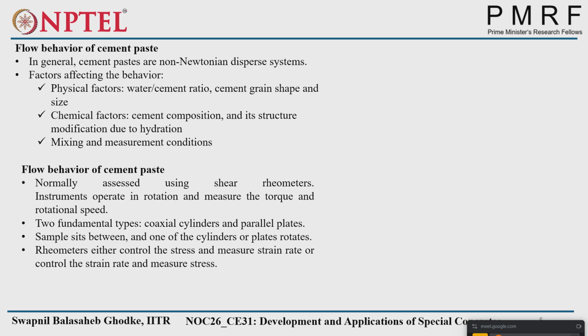Further, shear rheometers that are normally used generally operate in rotation. They rotate, that is, give the shear and measure the torque and rotational speed as raw data. Then we plot that data and go for further analysis. Two fundamental types of rheometer are generally used: coaxial cylinder and parallel plates. The sample generally sits in the gap between these two types of equipment. This sentence is important: rheometers either control the stress and measure the strain rate, or control the strain rate and measure the stress.